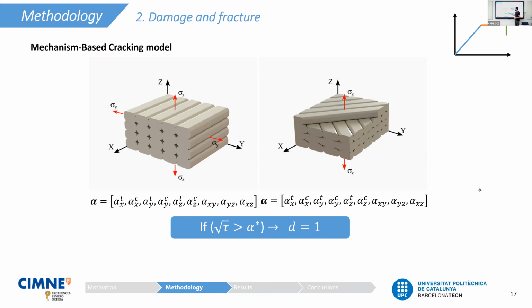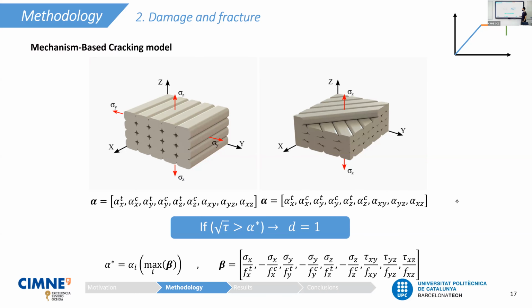The main question here is how are we computing this alpha star? Well, we are defining an alpha array of 9 components. Each component is used for each material direction, and we are distinguishing tension and compression, meaning we have one alpha parameter for X traction, one for the X compression, and the same goes for every single direction. And then we have 3 different alpha parameters for the shear. Then we are computing an array beta, where this array beta has again 9 parameters, analogous to the alpha array. And in each parameter, we are calculating the ratio between its corresponding stress value and its corresponding strength value. Again, we are distinguishing tension and compression, and we have the 3 shears here at the end.